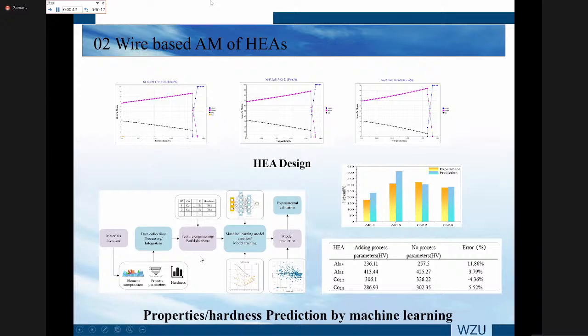So for example, the hardness, the microstructure. Here I give an example for two types of materials. One is about BCC plus FCC. We can see our prediction error is low. It's less than 10%.